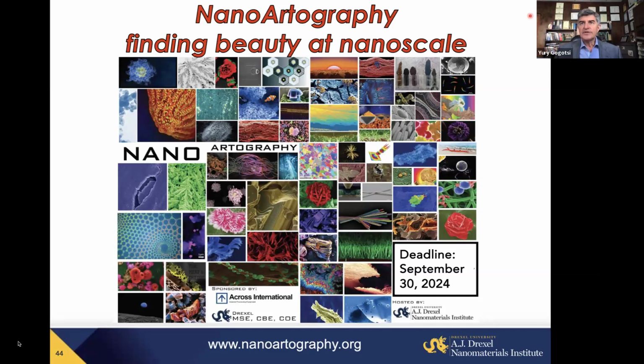But again, if you need a link to our papers, write to me and I will provide information. Thanks. Another question, can optical properties be enhanced by heterostructuring with 2D chalcogenides? Short answer is yes. People combined molybdenum disulfide, tungsten disulfide with MXenes. Moreover, I didn't talk about it today, but we can also make MXene with chalcogen on the surface. It will look on the surface like a chalcogenide, sulfide, selenide, telluride. But inside, there will be not just a metal, there will be a carbide layer. So it's a kind of a hybrid between chalcogenides and carbides and nitrides.